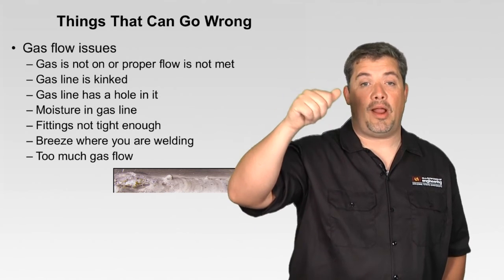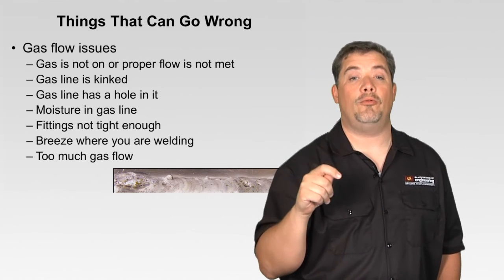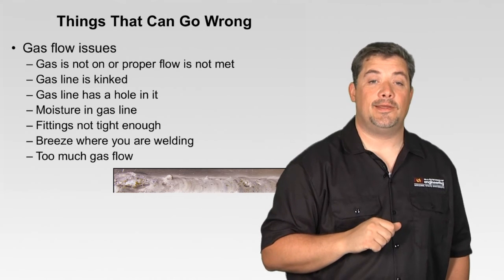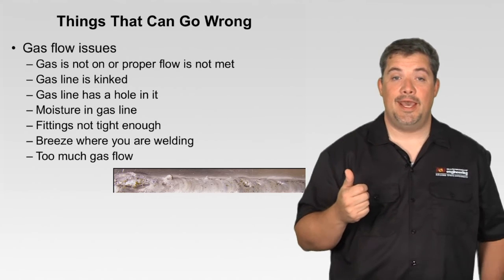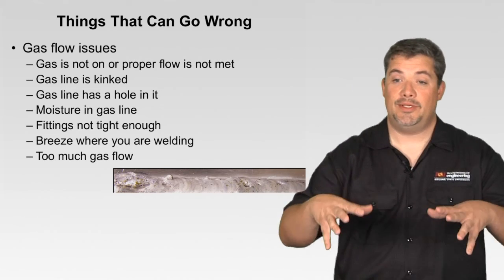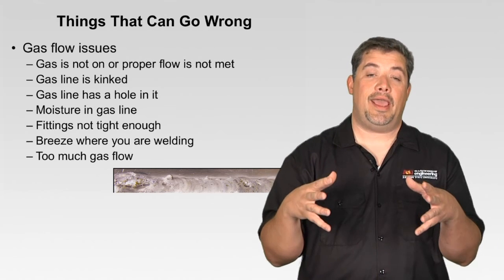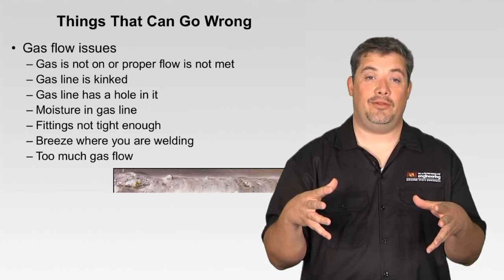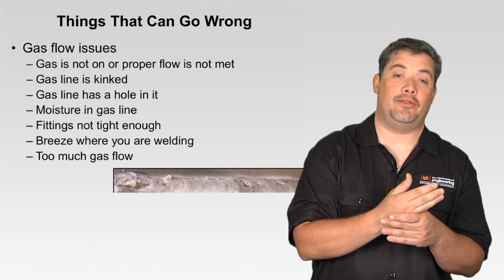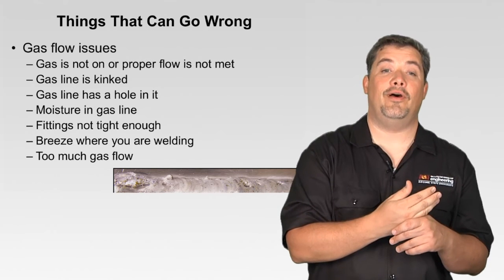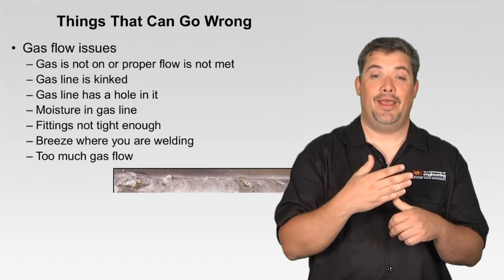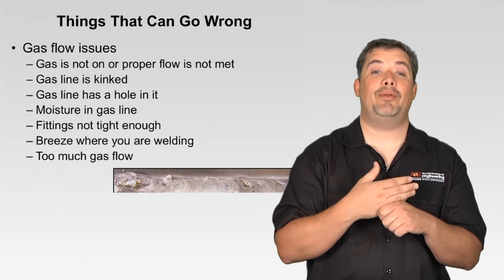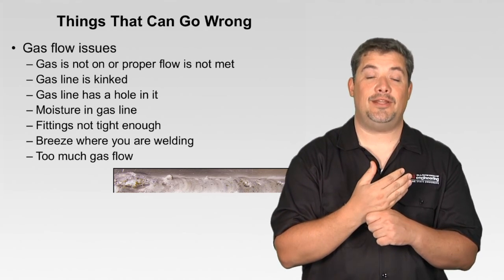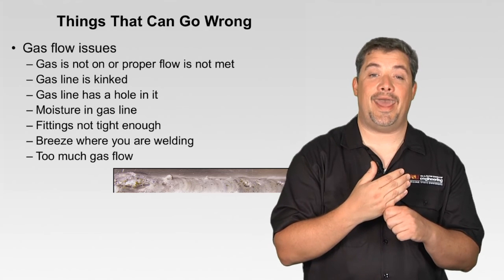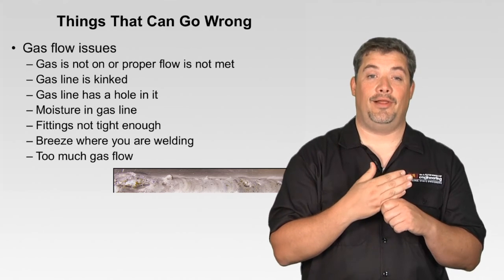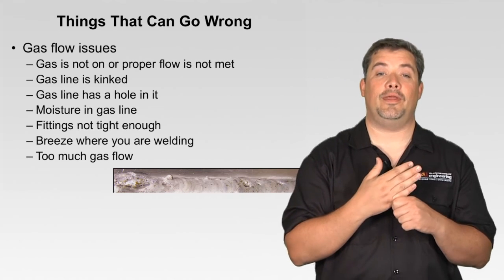You haven't got the proper standard cubic feet per hour flow rate set, or your gas line is kinked. And the gas line can kink pretty easily because in TIG welding we tend to sit down, in chairs with wheels on them, and we tend to roll around on those wheels, and those wheels actually roll over the gas hose on the TIG torch. They might even roll over the water coolant line on the TIG torch, causing my TIG torch to burn up. So I've got to be really careful where my TIG torch hoses are, so I don't kink that gas line or that water coolant line, to keep that weld quality up.